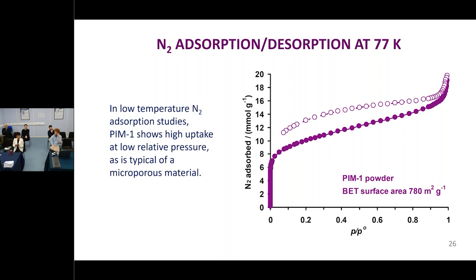But what we can see here is we take a typical sample of this PIM1 and apply the Brunauer-Emmett-Teller type analysis, BET analysis, which I'm sure many of you know about, you can come up with a value of surface area, typically 700, 800 square meters per gram. That's not all real surface, but these are pores. This is the amount of nitrogen it would take up, which, if it were a flat surface, it would be that area. But it's indicative of how good these are at pulling in little molecules.